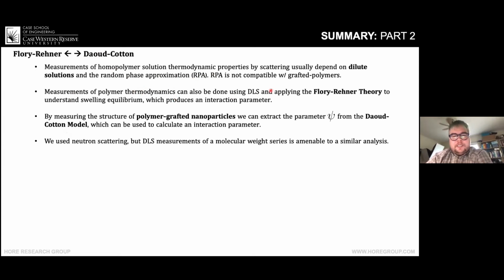If you do DLS on microgels and use the Flory-Rehner approach to understand how they swell, then you can get an interaction parameter out of that analysis. So the point here is that if we measure the structure of polymer grafted nanoparticles, we can extract that parameter psi, and that can be used to calculate an interaction parameter. So finally, we use neutron scattering, but the approach that we took to get the thickness of the brush can also be done with DLS measurements.